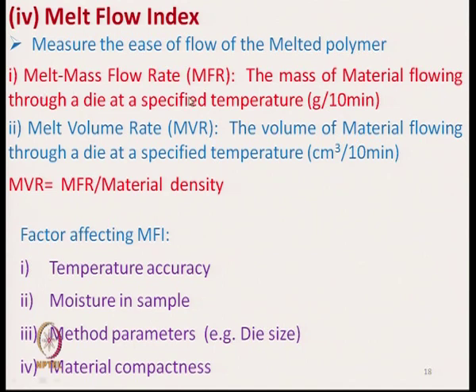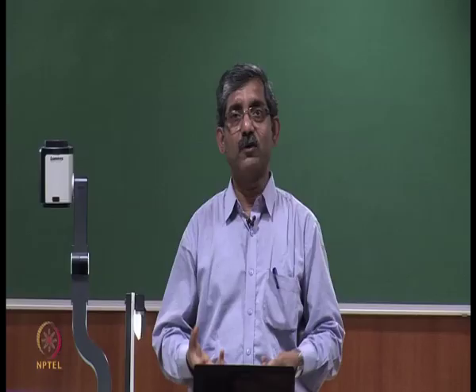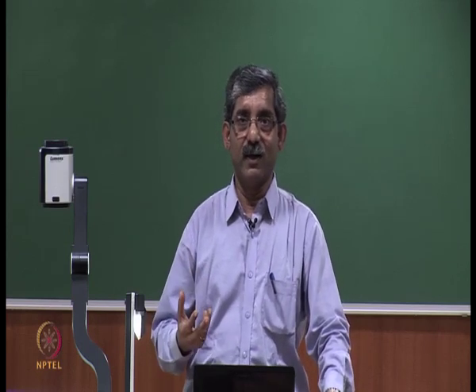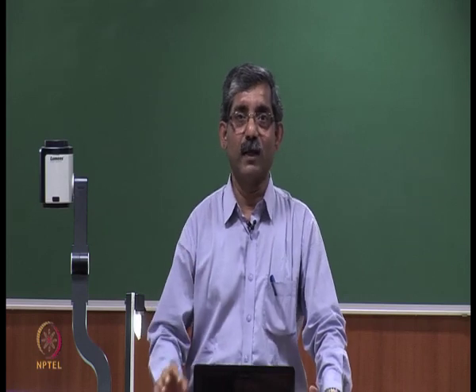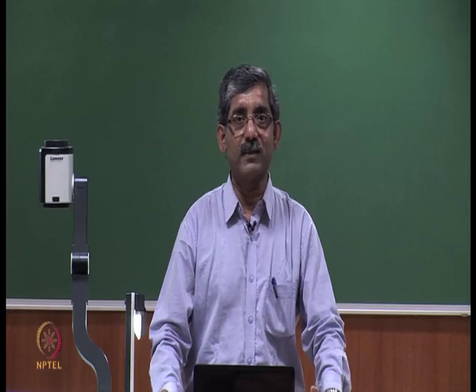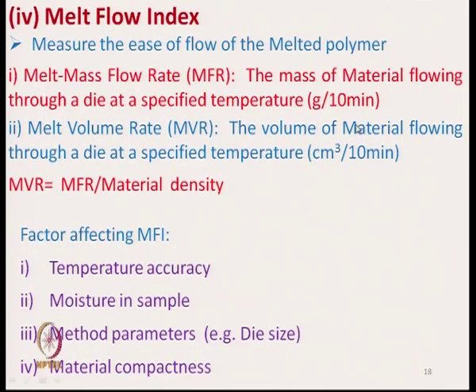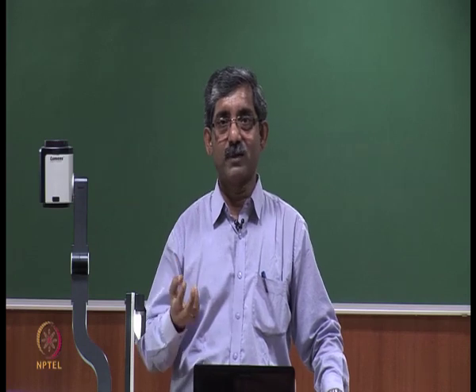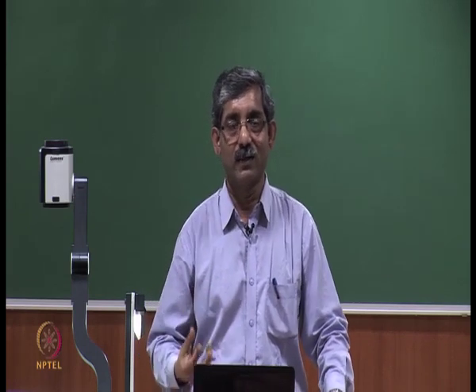Melt mass flow rate, called MFR, is the mass of material flowing through a die of a specific dimension at a specified temperature. The die specification may be different. So for a specific die size, the amount of molten material flowing per unit time, in general, is expressed in gram per 10 minutes. So for 10 minutes, how much molten polymer flows through a die, that is measured.